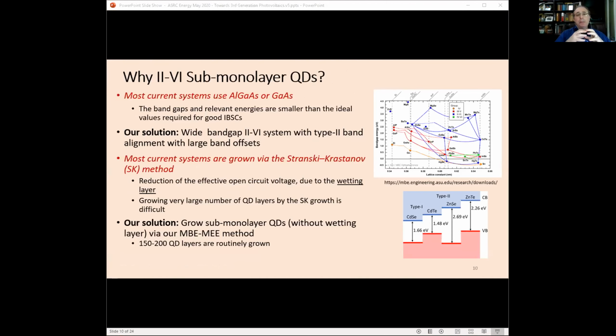Most of the intermediate band solar cell approaches which work right now, and it's actually skyrocketed in the last 5 or 6 years if you look at the literature, use the so-called III-V systems. If you look at this diagram here, these work at relatively low band gap. This is the number on the y-axis. So they work with about 1.3, 1.5 electron volts. As you remember, the requirement for the best intermediate band solar cells is close to 2 electron volts.